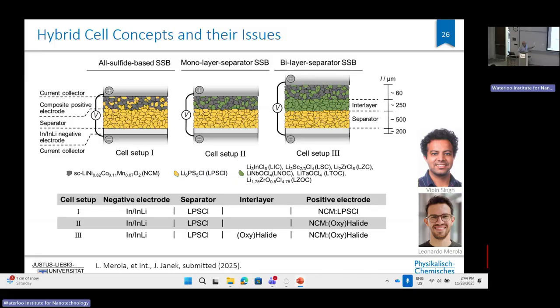They check different cell concepts where one is a benchmark, really a cell concept where only a sulfide electrolyte is being used, cathode, separator, no new interface, just one electrolyte. Then a catholyte that is typically a halide electrolyte that has more stability towards the cathode material, and again a sulfide electrolyte that has a nice SEI. And it is known empirically that, in fact, this cell concept doesn't work properly. You have to bring in a pure interlayer of the halide material at the end, so a kind of tri-layer cell, to really get it stable. And so they had quite some systematic work on that.